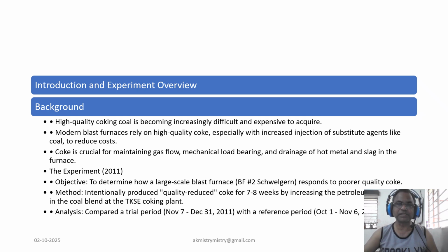To understand the risk, Thyssen conducted a bold experiment in 2011. For nearly 8 weeks, they intentionally produced quality reduced coke at their coking plant by increasing the share of petroleum coke in the coal blend. This inferior coke was then immediately charged into the large scale blast furnace number two. The study compares furnace performance during this trial period with a preceding reference period to precisely measure the impact of poor quality coke.